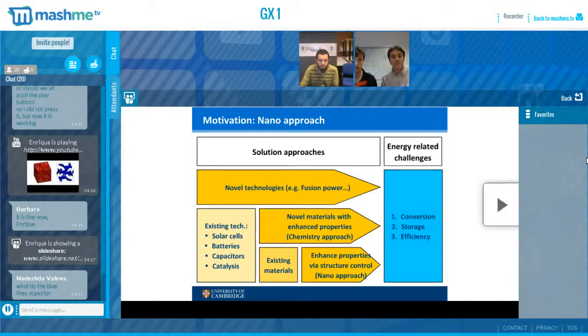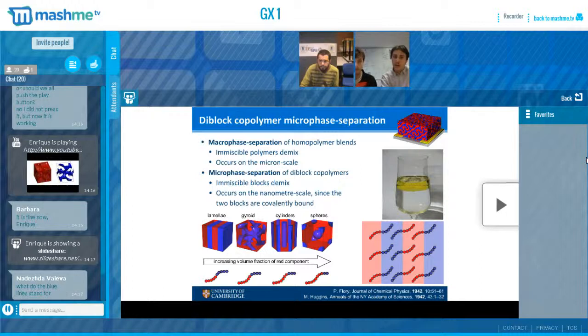And so there were two. On the left-hand side, there was the red structure. On the right-hand side, the blue structure. And the blue structure fits into the red one. So the red is the majority phase, and the blue network is the minority phase. So these are the two blocks. Like in this image at the bottom, this is a cartoon of a polymer with repeating units. So you have the red repeating units and the blue repeating units, and the gyroid structure fills the whole volume, and then we remove the blue structure. And you can draw these two different structures separately. So I hope this clarifies the question.